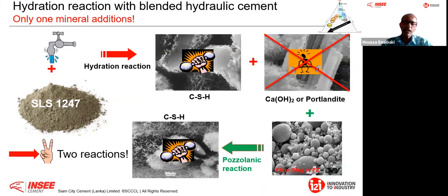You have two reactions. That is why if you test, let's say, blended hydraulic cement after 28 days, if you go to 56, 91 days, 6 months, 1 year, we have a lot of data we can share with you. You see that the strength just keeps going and going. You develop a concrete at 40 megapascal, you end up after 1 year with 80 megapascal. Therefore, the additional strength, indeed, you don't need it, but you need it to self-heal, to secure your concrete bridge or your concrete road or your balcony or whatever you build for durability regarding this exposure condition, especially when you have reinforcement.